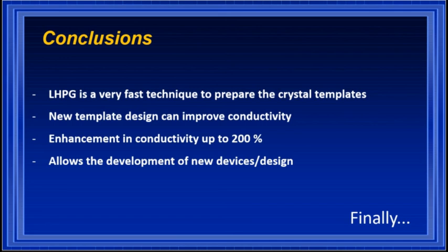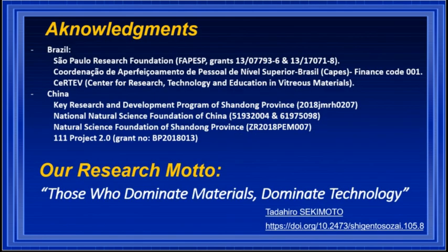In conclusion, the laser heated pedestal growth, since it's a very fast crystal growth technique, is a good one to prepare the crystal templates. The new template design, we have shown, can improve the ionic conductivity in solid electrolytes. This enhancement in conductivity can go up to 200% in our case, and this might allow the development of new devices and designs.